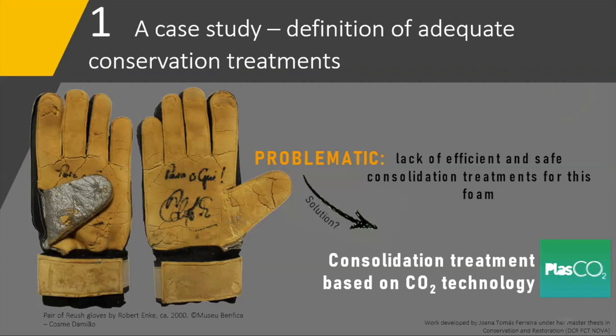Then, as our preliminary consolidation tests with more traditional approaches such as nebulization and facing were not satisfactory, and a lack of efficient and safe consolidation treatments for this foam was detected, we also took the opportunity to assess the potential of CO2 technology as a vehicle for the consolidation of the foam. Promising results have been obtained with the combination of CO2 and a PVAC as a consolidant, but more tests are still being carried out, and we hope in the near future we can find a solution for this challenging case.